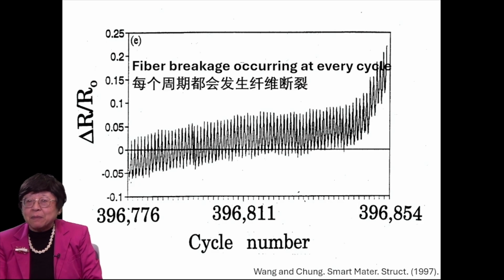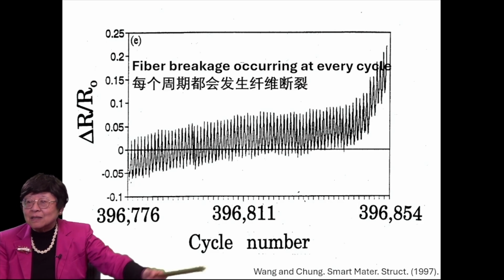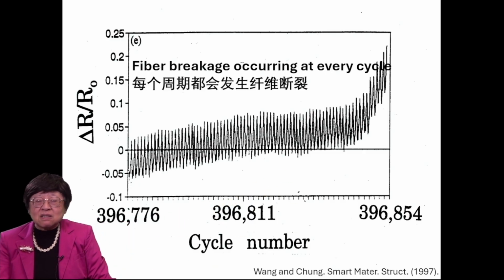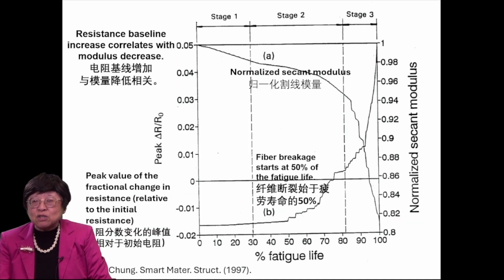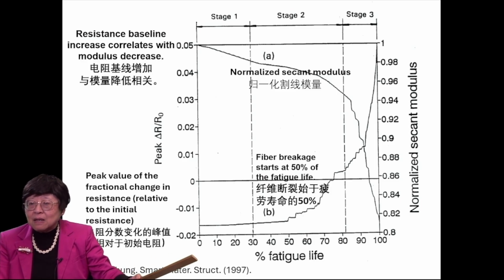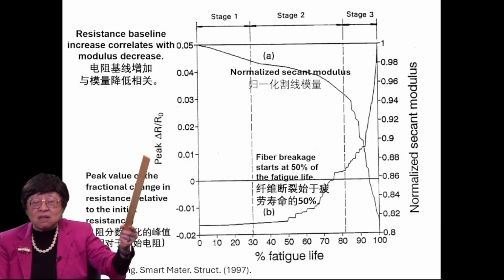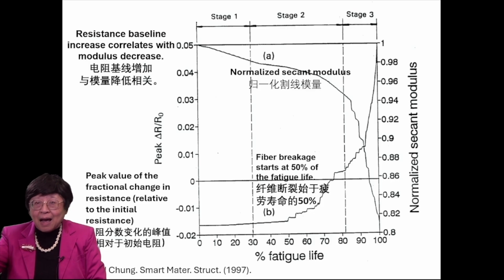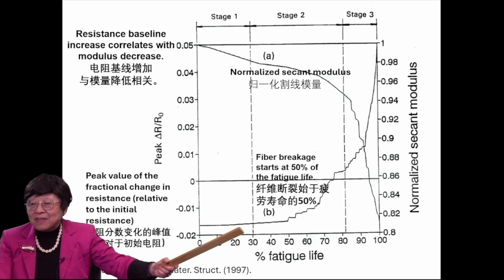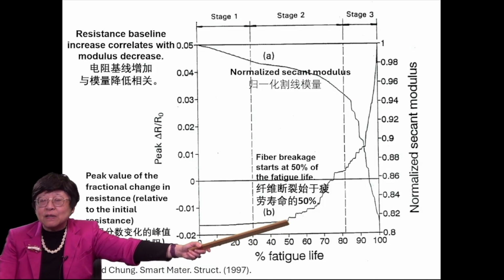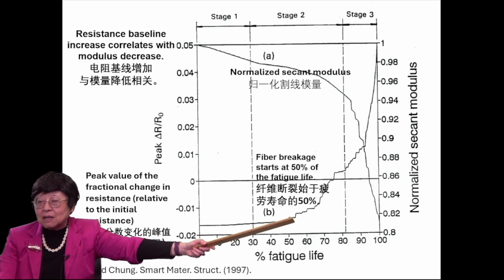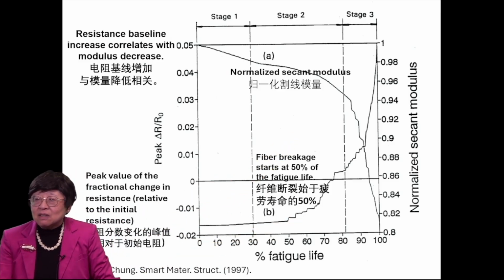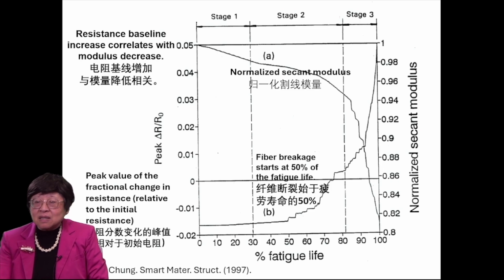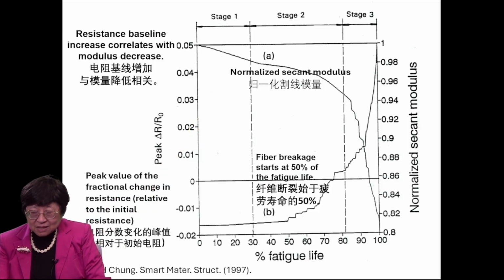So the baseline resistance climbs up incrementally in every cycle until it's close to breakage, and the baseline resistance goes up a lot. So we can track by resistance measurement the complete fatigue life. This shows the complete fatigue life, and the peak fractional change in resistance is shown. By peak, I mean it's down, up, and that up, that's what I call the peak. We find that resistance has the first spurt of increase around 50% of the fatigue life, and it comes in spurts, and later on it's continuous, not in spurts. Along with this increase in the resistance is the secant modulus decreasing, thus confirming that indeed we have damage occurring.